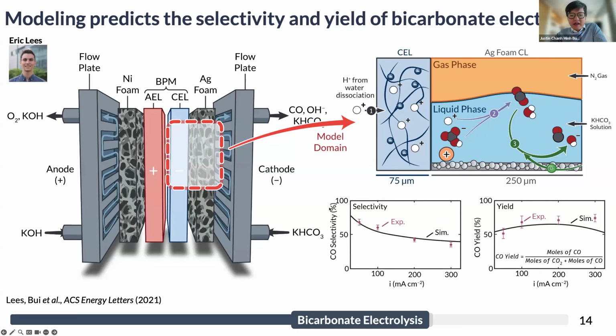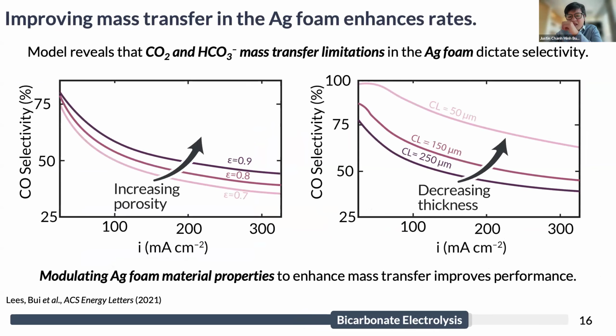You can see here that as I increase the current density, my CO selectivity decreases, and my yield has this local optimum with respect to the partial current density. Ultimately, we want to be able to get to a point where we have very high yields and high selectivities to our value-added product of CO. And so again, we're able to use this model to understand how to improve the performance of these devices. And what we see is that the model reveals that the mass transfer of CO2 and bicarbonate within the silver foam are the primary dictators of the selectivity of this reaction.